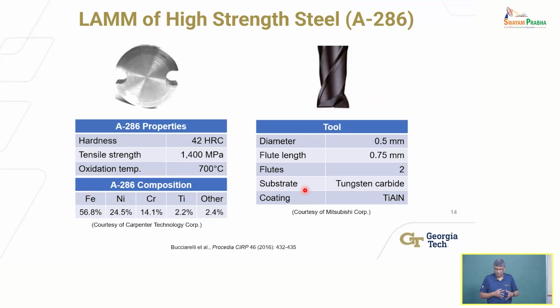Now that was A2 steel. There are other types of materials, right? Every material will behave a little differently in terms of how it interacts with the laser. This was for an industry project where they were interested in those fasteners you saw, in this case made out of A286, which is a high strength steel. It's an alloyed steel with high nickel content. You can see the nickel content is 24.5%, which is quite high, okay?